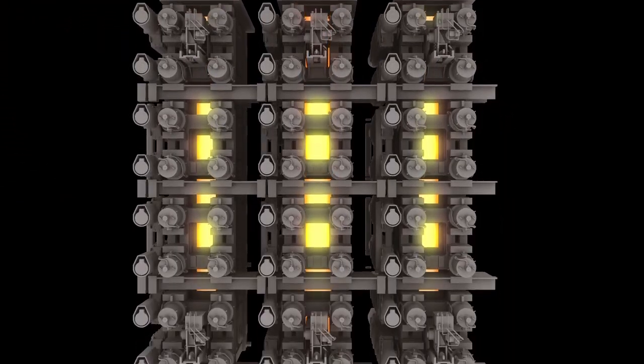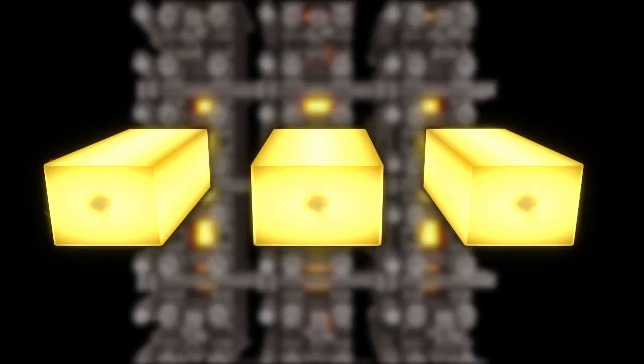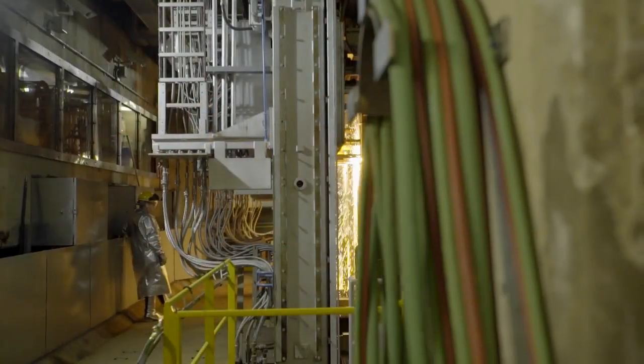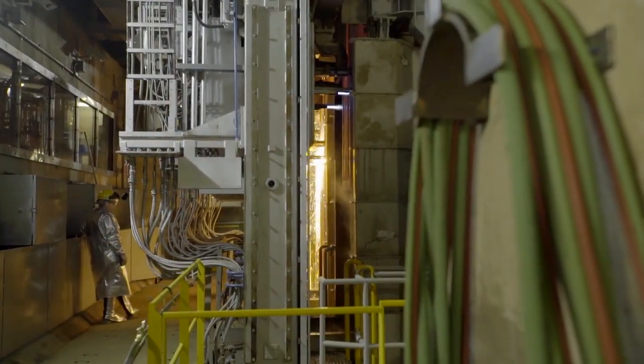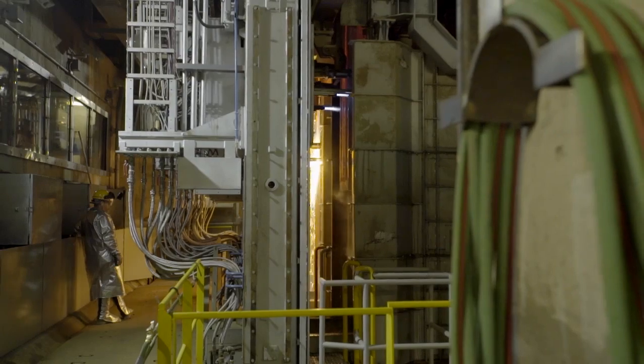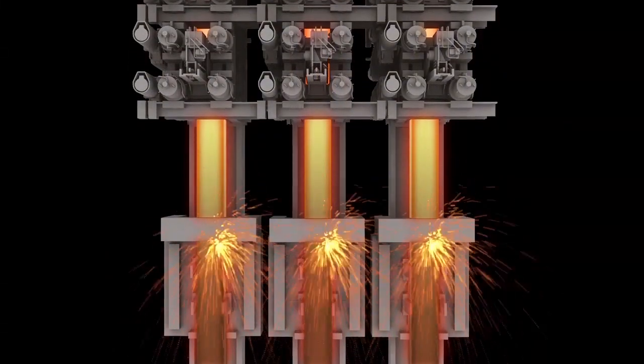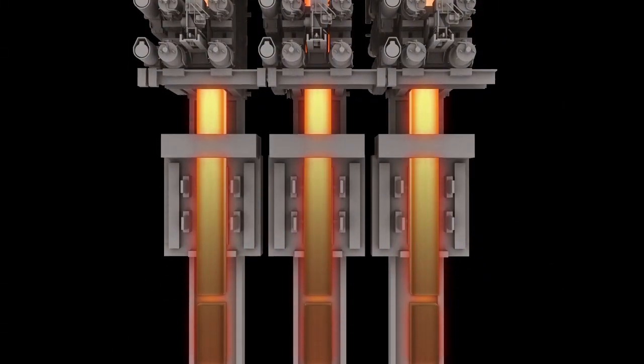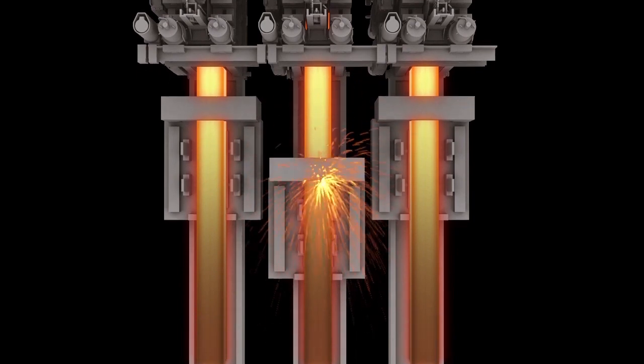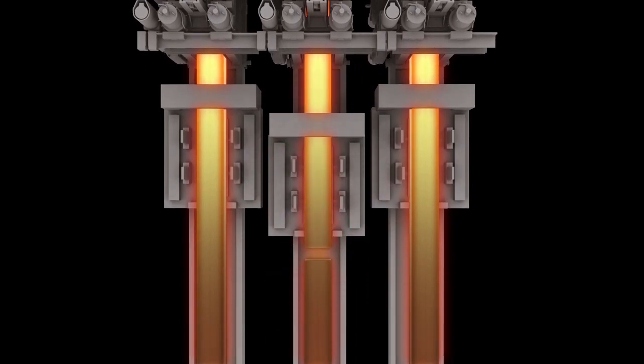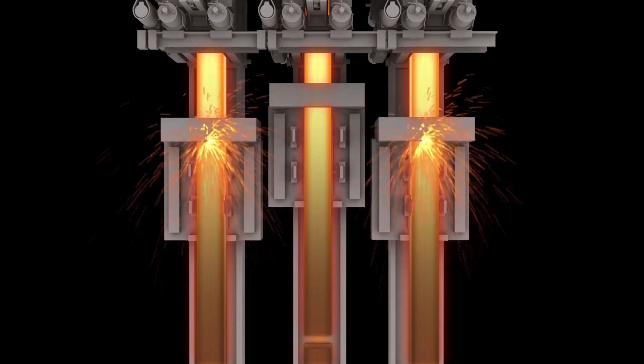Several of these rolls can apply soft reduction, which is a slight squeezing of the bloom shortly before full solidification. This provides the bloom with a superior solidification pattern and minimizes carbon segregation. After the strand exits the last mechanical soft reduction rolls, we cut it to size using a torch cutting machine. This machine clamps and follows the bloom as it travels to make a straight cut across the bloom face. We can customize the bloom length to allow for optimum cutout in a rolling mill.